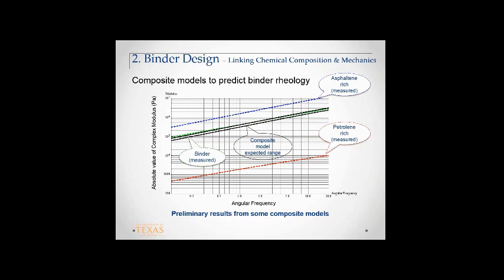What does happen in the real world is oxidation, for example. Oxidation consumes some of the lower nonpolar fractions and produces more of these, right? So what is an oxidized binder? An oxidized binder is nothing but a binder where this is being consumed and that is being produced. So you can take this knowledge and apply it to what happens to the binder rheology when it oxidizes. What is a recycled asphalt binder mixed with a virgin binder? It's a binder that is rich in this mixed with a binder that is not so rich in that. So you again take these same fundamental ideas and you can start applying them to these realistic systems.